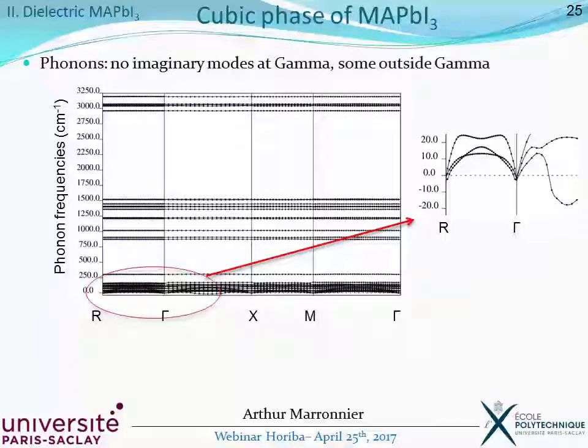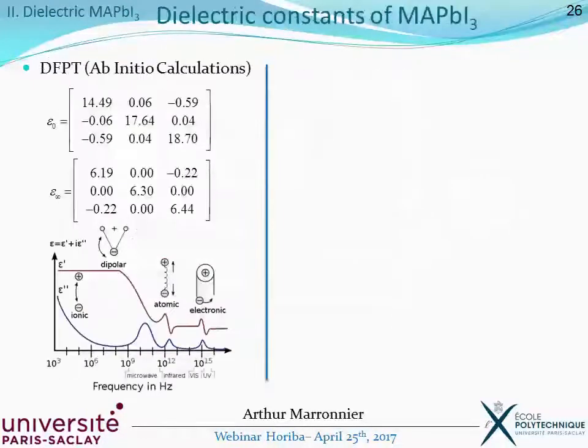So it was easier this time to derive the dielectric constant. We don't need any corrections. And here are the results. You can see that we obtain a quite high value for epsilon static, epsilon 0, around 17, 18, which means that this hybrid perovskite behaves as an inorganic semiconductor, which could explain why it has shown such interesting